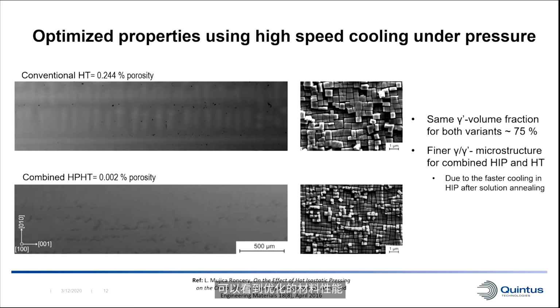And the optimized material properties can be seen here by the fine microstructure in the lower end of the slide. You can see that the initial porosity for the conventional production route is about 0.25%, with a nicely distributed gamma prime structure. However, with the high pressure heat treatment, we can pretty much eradicate the porosity completely and obtain a very, very fine microstructure. You can read more about this in the papers that the University of Bochum have already published.